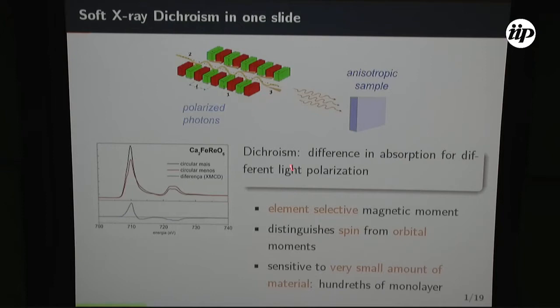And the best-known dichroic technique in the soft X-ray range is the circular magnetic dichroism, that I would like to explain quickly here. It's very simple. The measurement itself is quite simple. You measure one absorption spectrum, in this case around the iron edge, with one helicity. It's in Portuguese here, so one helicity is black and another helicity is red. For those of you that are not used to the technique, the dichroic signal is the difference between both.